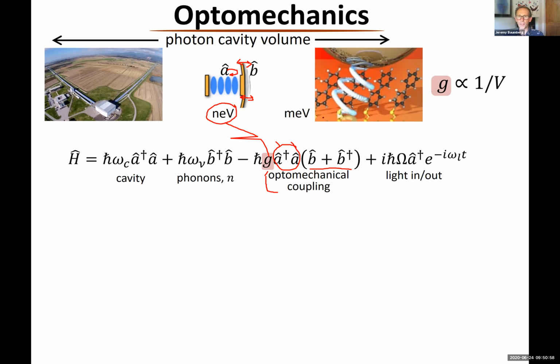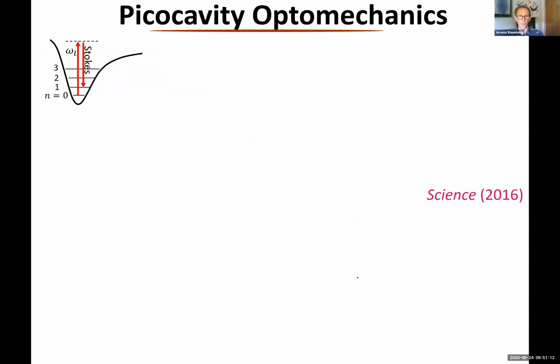The interesting thing about the geometry I've been showing you, this nanoparticle on mirror, is that the equivalent G, which is proportional to 1 over the volume here, is therefore scaled up very, very strongly. So now it becomes comparable to room temperature. So we can start to see some of these effects at room temperature. The way we do that is we look at this system here, which is looking at the vibrations of the molecules.